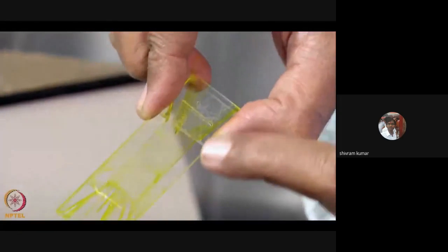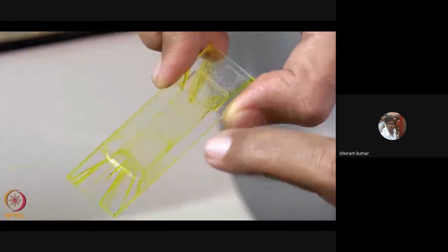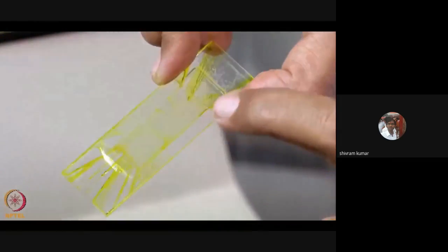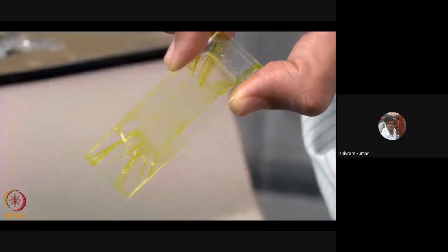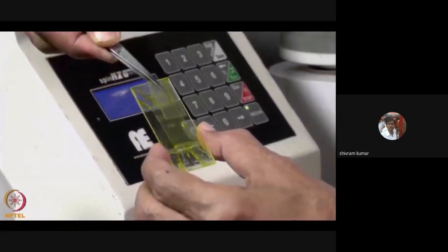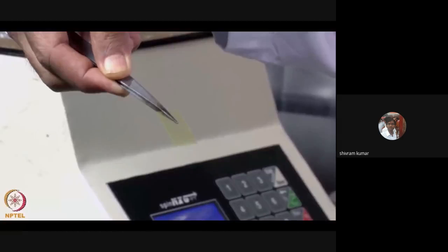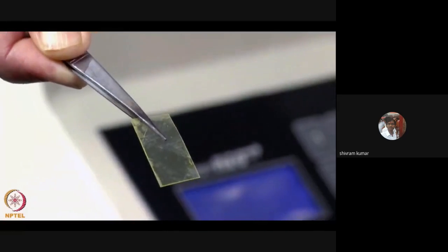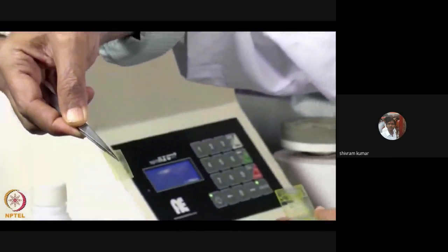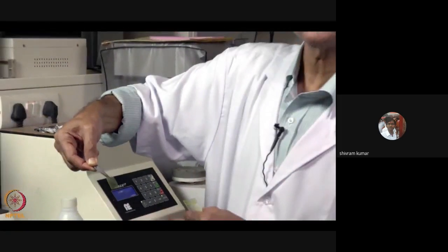As you can see, curcumin and PVP mixed material has been well coated on this polyester, and now we can peel out this polymer from the glass slide. This is the polymer polyester coated with the PVP and curcumin. So this will have antibacterial activity, so we can use this for preventing biofilm formation on polyester surfaces.